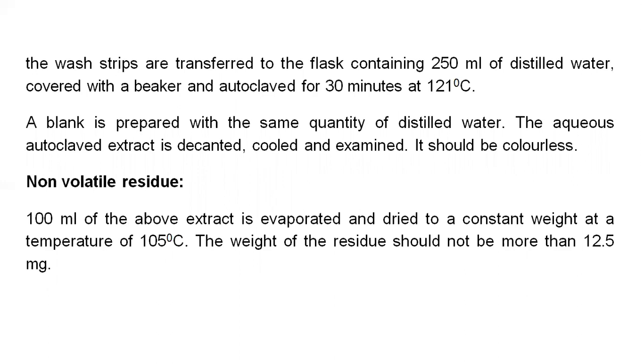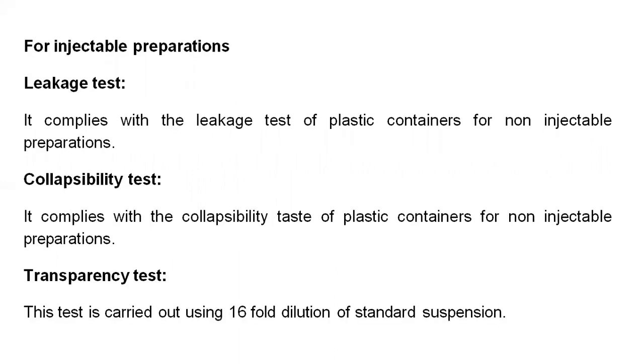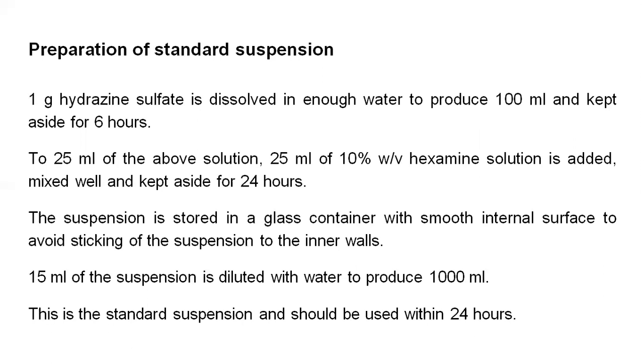The weight of the residue should not be more than 12.5 milligram. For injectable preparation, leakage test: it complies with the leakage test of plastic containers for non-injectable preparations. Collapsibility test also complies with the collapsibility test of plastic containers for non-injectable preparations, and the transparency test is carried out using 16-fold dilution of standard suspension.